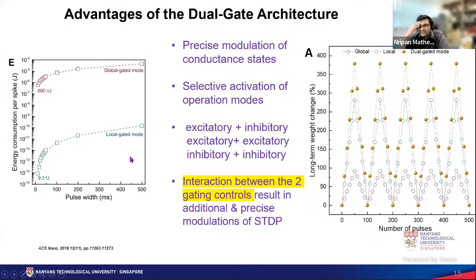Because the ion gated mode is operating at very low voltages, and if you work with small enough pulse widths, your energy consumption per spike can be very small. But again, please note that the pulse widths that we normally work with are still pretty big. Initially, they were limited by the Keithleys or the electronic equipment we were utilizing. Now we are moving on to trying out faster and faster pulse widths.